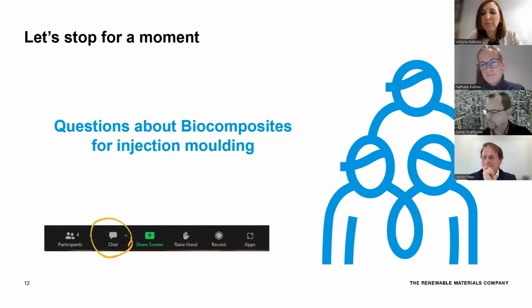Great. Do you have experience molding a one-piece chair? A one-piece chair? I understand. Like a full piece? Yes, molding. Yes, Daniel, we have that, right? In the office even. We have that, and we have had the most success when we have used less fibers. We have some materials with only 30% fibers, and those have been the easiest to injection mold into a one-piece chair, of course, since the size is quite big. But today we could probably even use 40% material for that type of application, I would say.